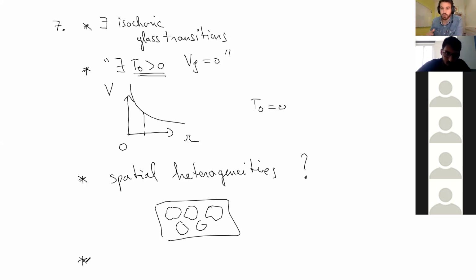And finally, and perhaps above all, the free volume description and the dynamical and kinetic descriptions of the glass transition are interesting to most experimental physicists, okay? This is a fact. People doing experiments with glasses are really measuring at the moment where nothing flows anymore. It's really important to them. Some physicists think that behind this boring slowing down of materials, there is a real phase transition somewhere, hidden, okay? The existence of a critical point with a real change of phase in the system.